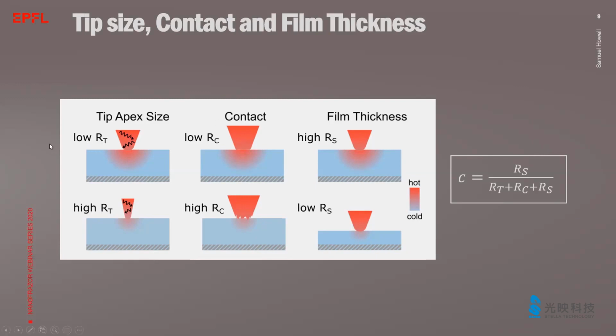So the heat transfer across the tip sample interface is a parameter that is most difficult to calculate or to measure. It depends on the atomic roughness of the tip and the sample and how efficiently phonons can be transferred between the two materials, the tip and the film. So calculating the contact resistance is further complicated because during patterning, it can change due to tip wear and contaminations.